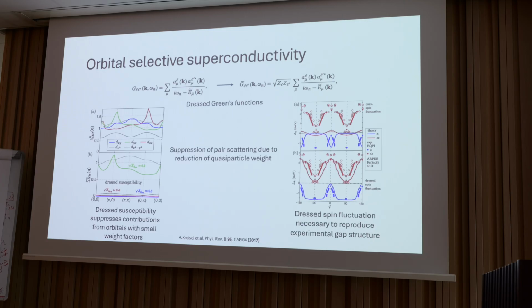including the spectral weight contribution suppresses contributions from orbitals with small weight factors. And they basically need to have these dressed spin fluctuations to reproduce the experimental gap structure that they determine. Yeah, but the idea being suppression of pair scattering due to the reduction of quasi-particle weight.